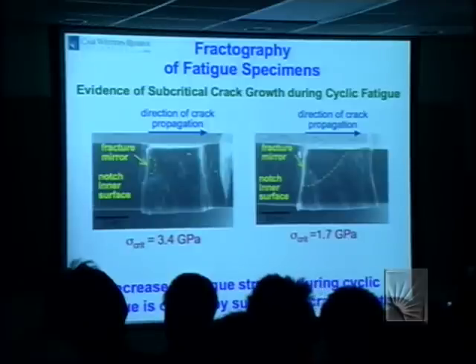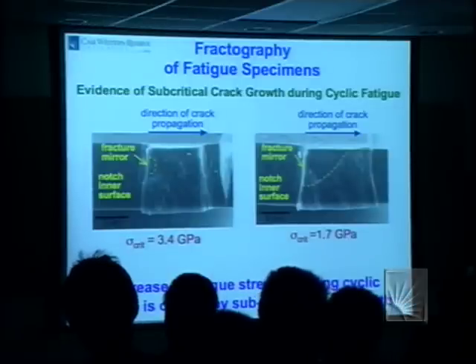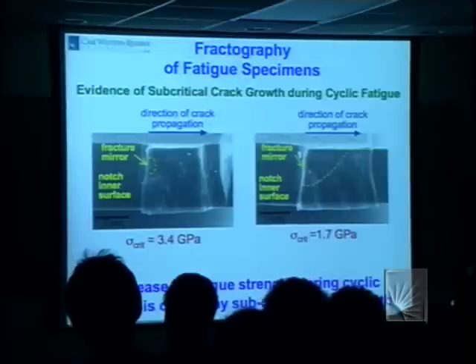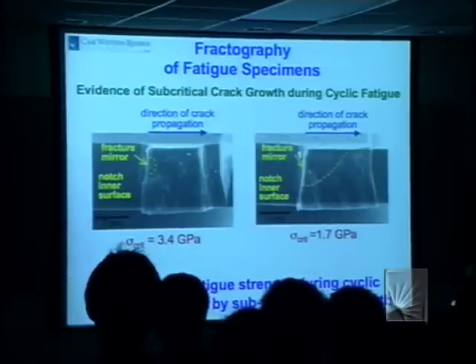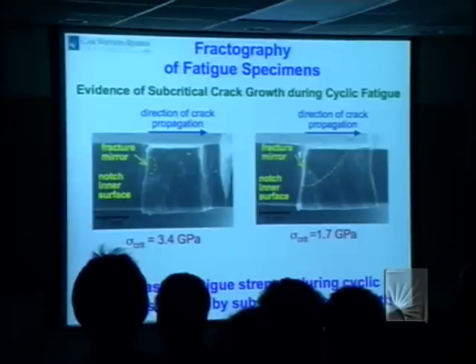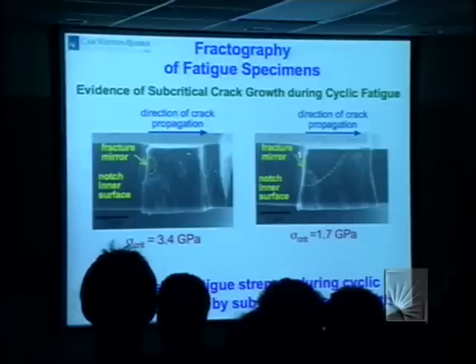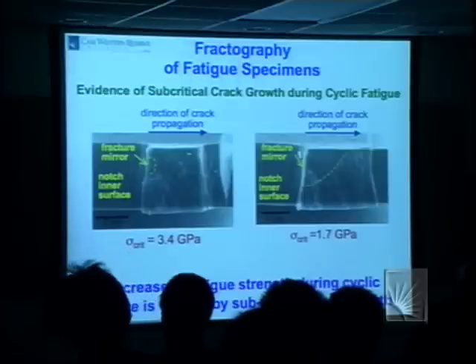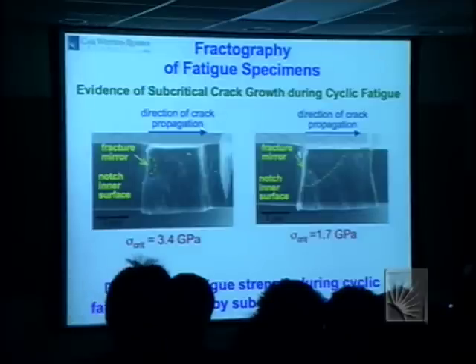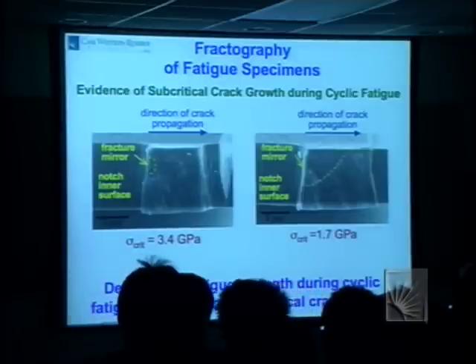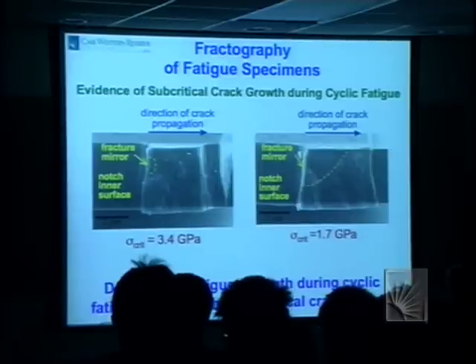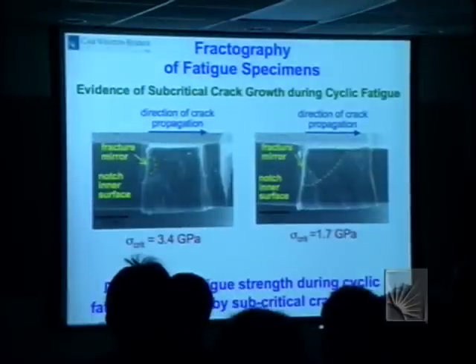And it's peculiar because this kind of behavior is well known in oxide ceramics or in oxide glasses, where it's very clear that you get subcritical crack growth due to a form of stress corrosion. A crack in the presence of water vapor, which is almost always around us, can fail subcritically, and the crack will slowly grow due to this kind of stress corrosion cracking. But silicon is immune to this kind of thing. As far as we know, there's no evidence that the strength of silicon is sensitive to the presence of moisture, either liquid water or atmospheric moisture. Very different from oxide ceramics and oxide glasses.